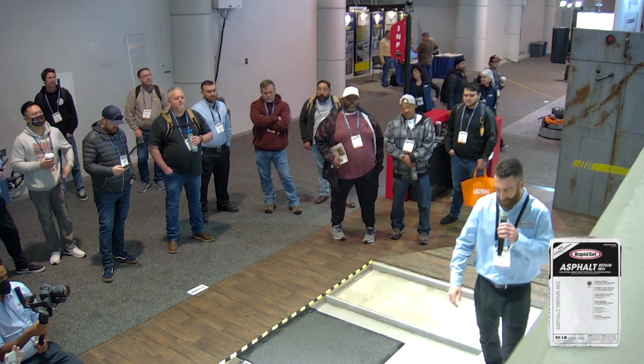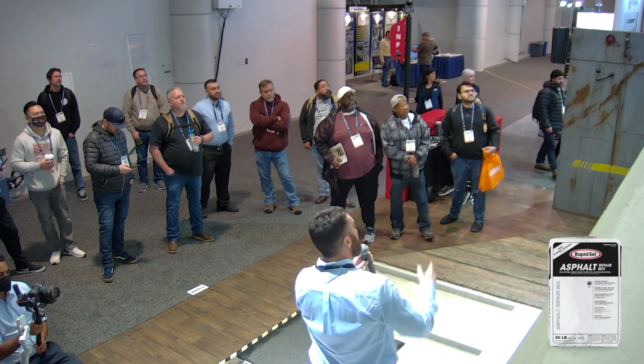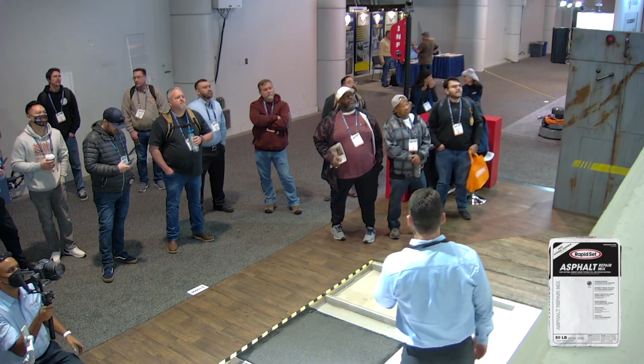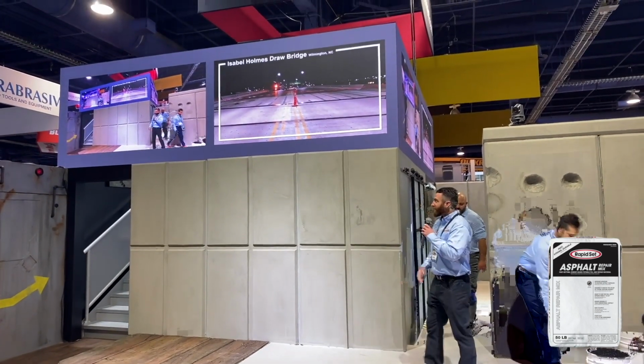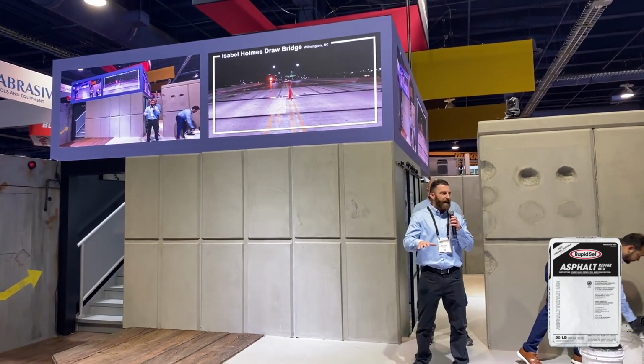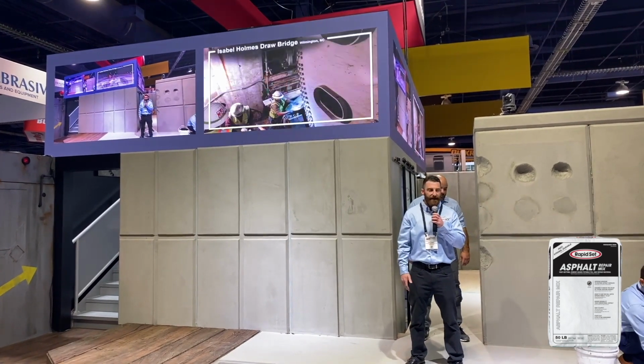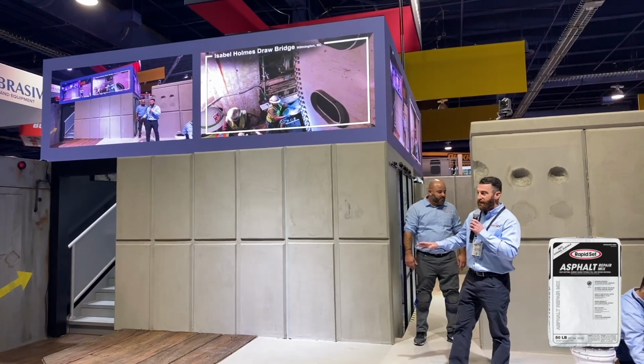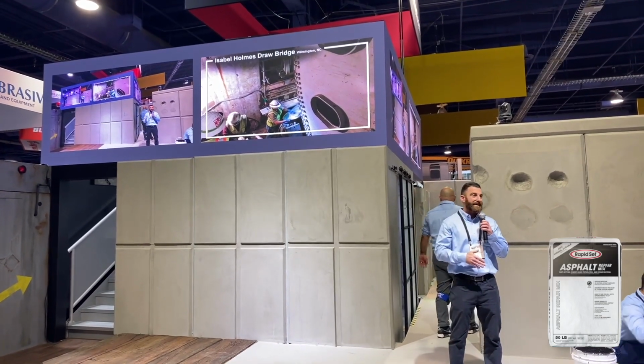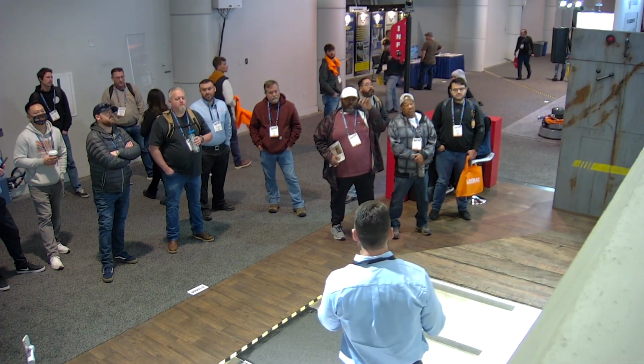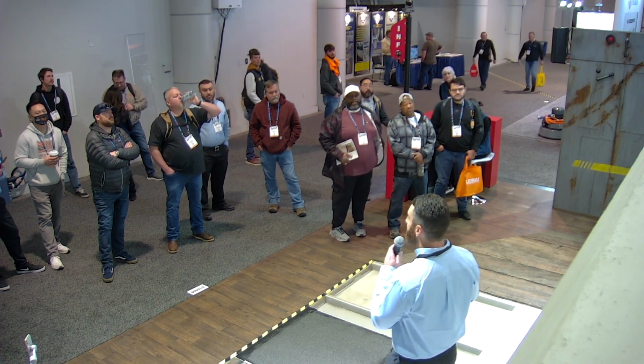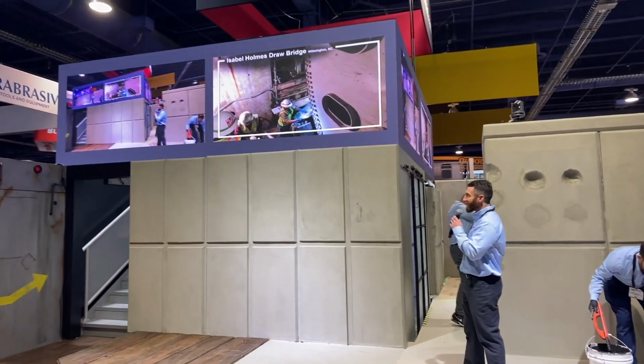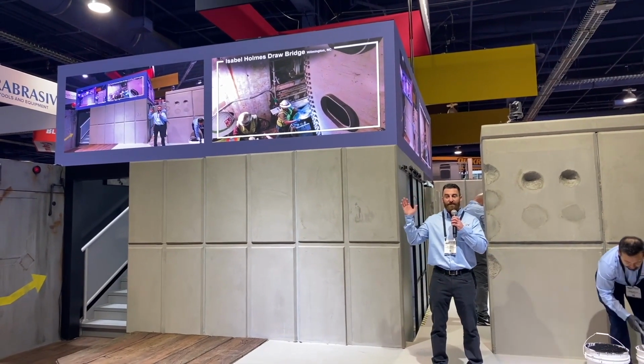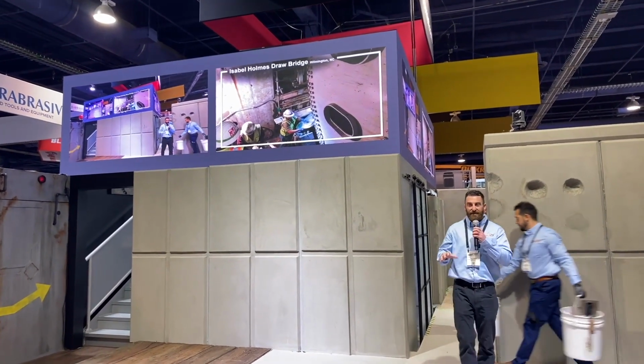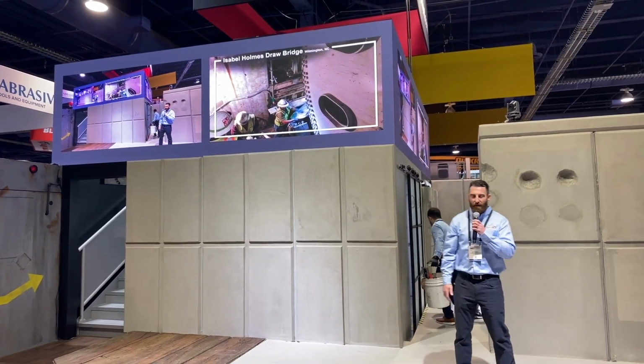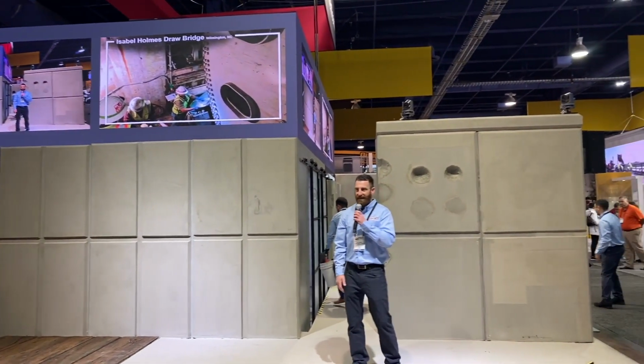I think we've got some projects on the screen. Let me see if I can see them here. The Isabel Holmes Drawbridge. This is in Wilmington, North Carolina, and NCDOT said that they had to do some repairs. It was sitting on these bearing pads which were anchored to concrete, and the concrete was deteriorating. But the DOT said, well, you can only close this bridge to traffic from 7 p.m. to 6 a.m. on weekdays, and if you open late, it's going to be a $2,000 fine for every 15 minutes late opening. So they specified the DOT concrete mix. It allowed them to open the drawbridge, perform the repairs, gain structural strength, and close the drawbridge each morning to open it up to traffic, and not once did they pay a late fee.